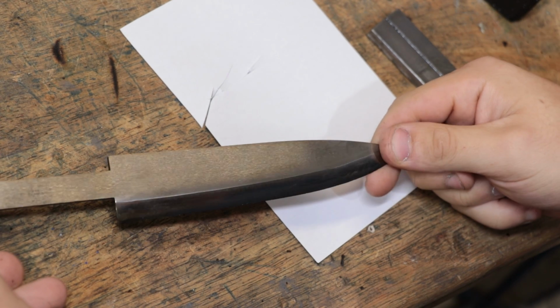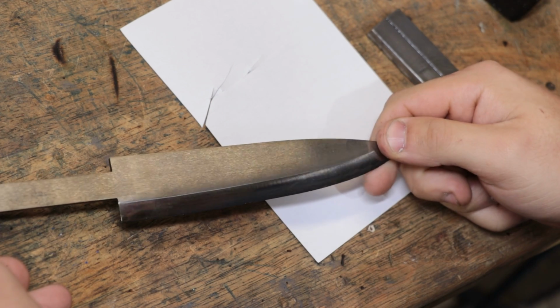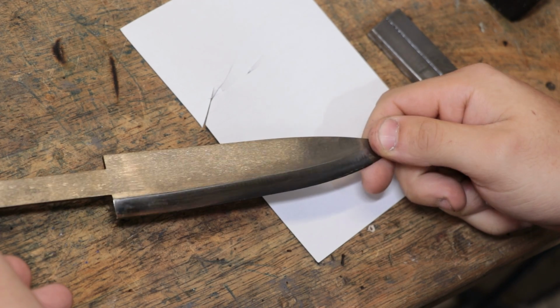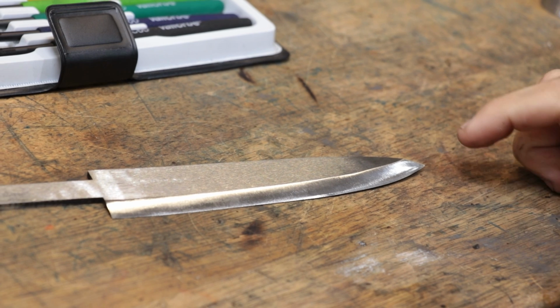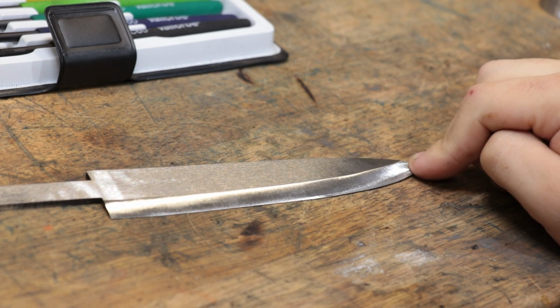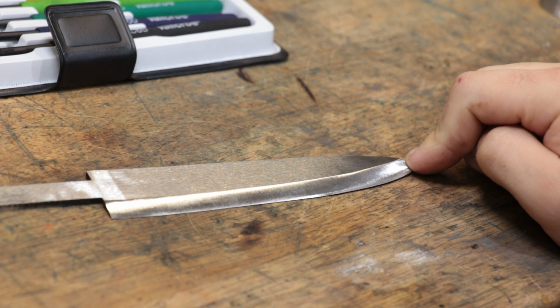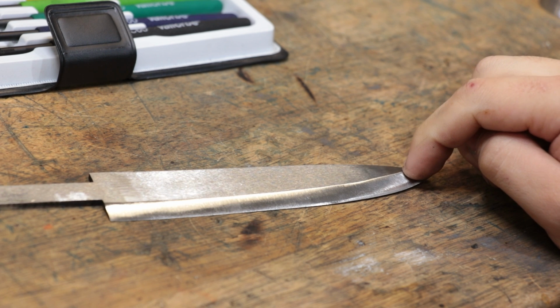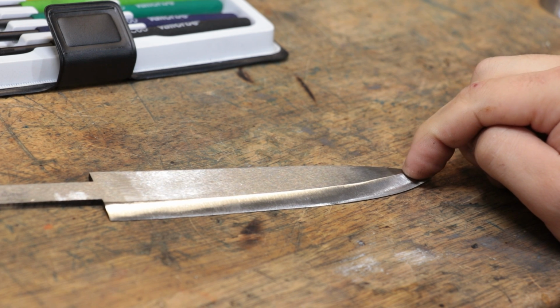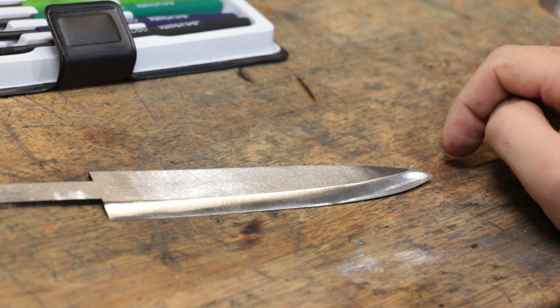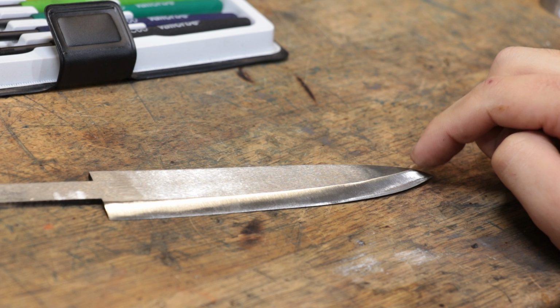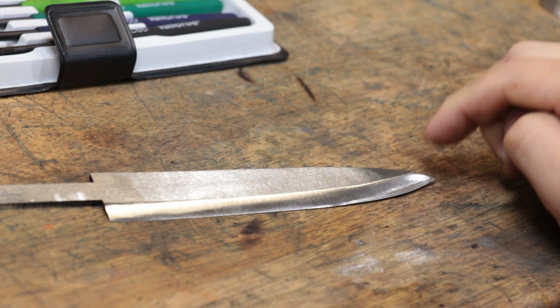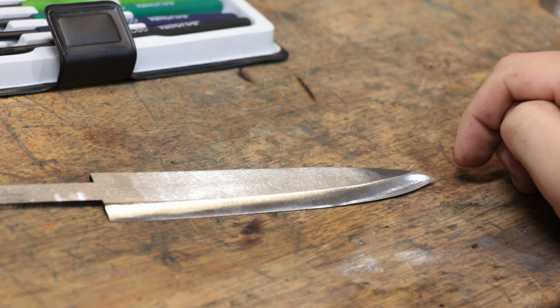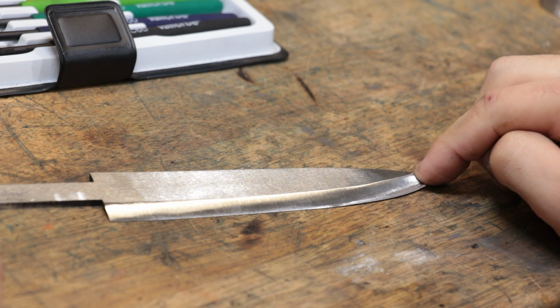Thankfully though, once it has been tempered through, it is much more receptive to being sharpened without shattering. Unfortunately, it does look like the blade has warped a little bit during heat treatment. Now, since the core is unhardened and still quite ductile, I could probably bend it back into shape, but I don't want to risk the blade cracking. It's probably hardened all the way through, and if I tried to bend it too far, it would probably crack on me. It has been tempered, but it is still quite hard, so I don't want to risk it.